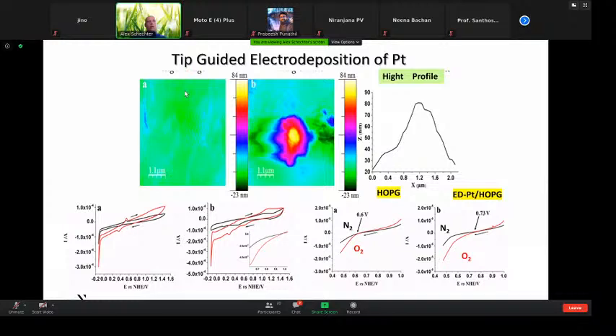At first, what we did is we wanted to see if we can control the reaction. So here is an empty carbon electrode, HOPG electrode, and we put a platinum solution on top of that electrode, and we were able to direct the deposition of platinum by applying potential. Here you can see the differences between nitrogen and oxygen. This is before, this is the bare HOPG and the platinum.